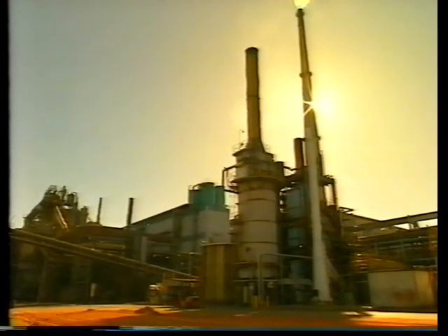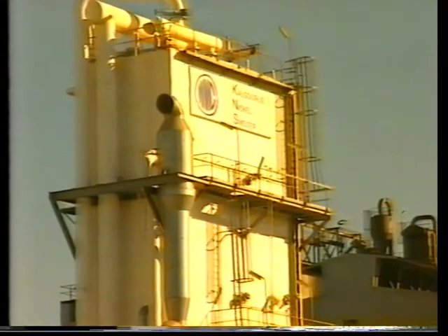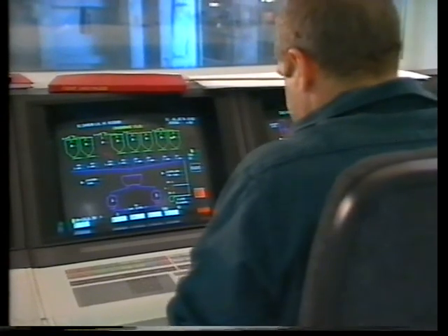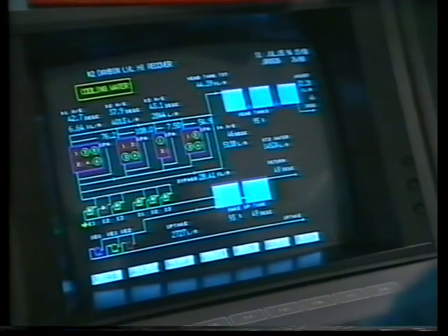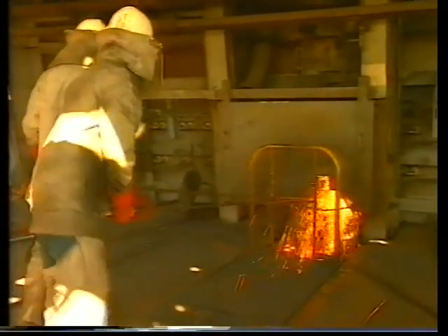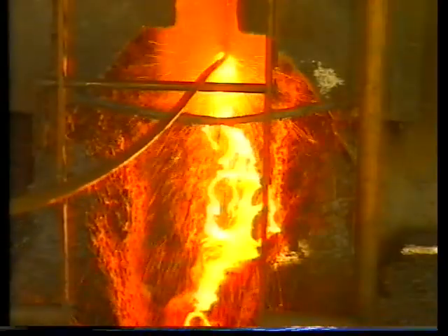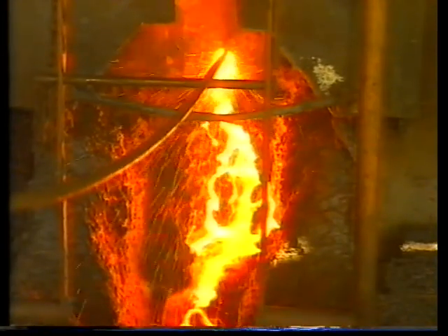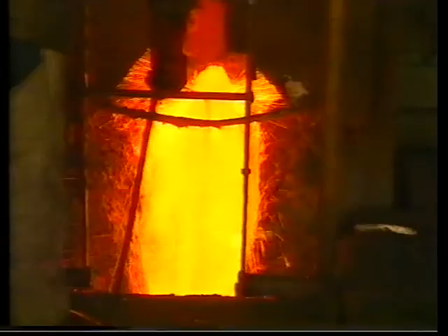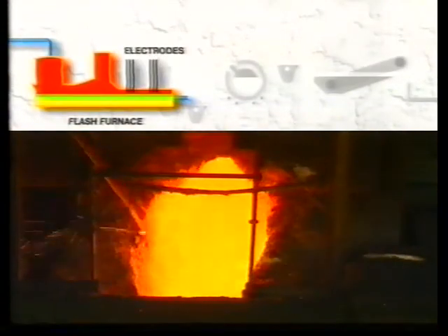The heart of WMC's value-adding process is its Kalgoorlie smelter. Opened in 1972 and continually upgraded since, it can presently treat 80,000 tons of nickel in concentrate per year. The plant uses an energy-efficient process which makes use of the fuel value of the sulfide concentrate. As the material is mixed with flux and fed into the chamber at temperatures up to 1550 degrees Celsius, it oxidizes almost immediately and flashes to a molten state. It's this spectacular change which gives the process its name, flash smelting.